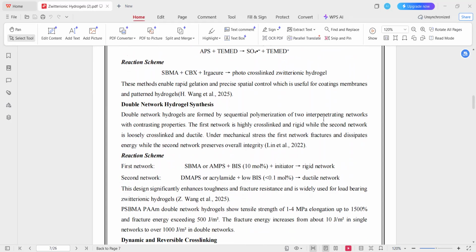When the zwitterionic polymers are incorporated into one or both of these networks, the hydrogel achieves a combination of high mechanical strength and excellent anti-fouling behavior. In practice, the first network is synthesized by using a high concentration of crosslinker, while the second network is formed using a much lower crosslinker concentration. This design dramatically increases the tensile strength, elongation, and fracture energy, making the double network zwitterionic hydrogel suitable for load-bearing and mechanically demanding applications.